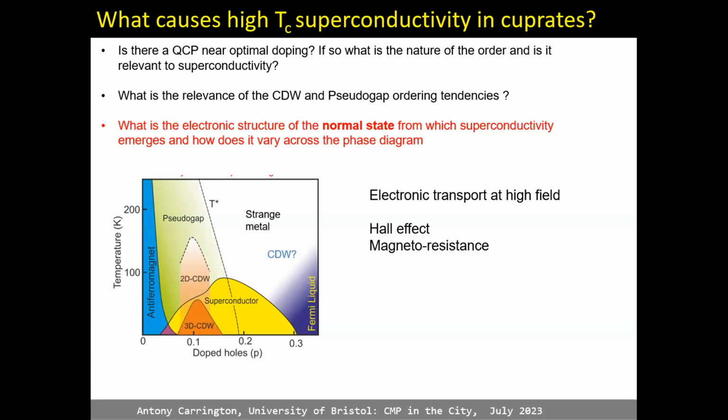Oh yeah, I was telling you what causes high temperature superconductivity. The way I look at this phase diagram is we've got some antiferromagnetism here, and if we start from this side, then as we approach this point here, the antiferromagnetic fluctuations grow, and so pairing for superconductivity grows, until you reach this point here, at which point parts of the Fermi surface start to become incoherent, and that reduces Tc. So from that perspective, the most important part of the phase diagram to study is this part over here, and all this part here is some irrelevance where there's some competing phases.